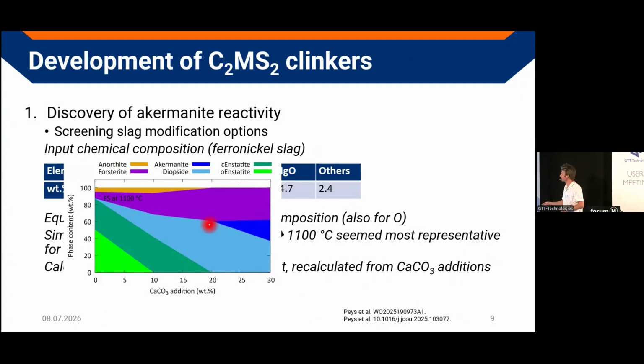This is just the simulations at 1100 degrees, because afterwards we saw that this one corresponded best with the XRD results of the clinkers that we made, of the slags that we made. Here it was still slags. So you can see that we go from a very pyroxene-rich material. You see enstatite, that's the magnesium silicate pyroxene. You go towards more the diopside, a calcium magnesium silicate pyroxene mineral, towards the akermanite, which is this composition.